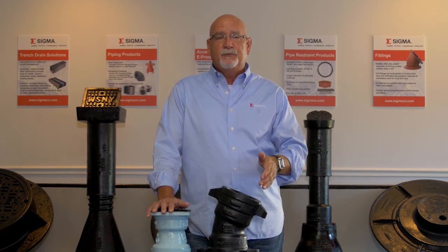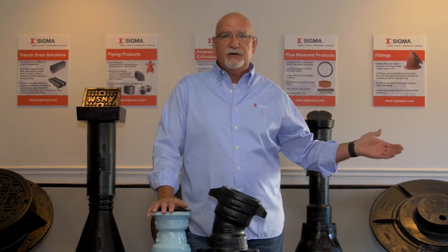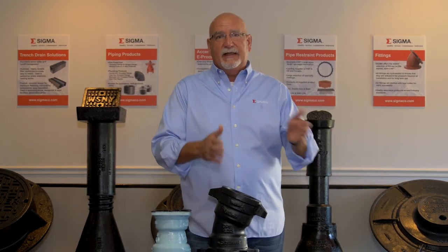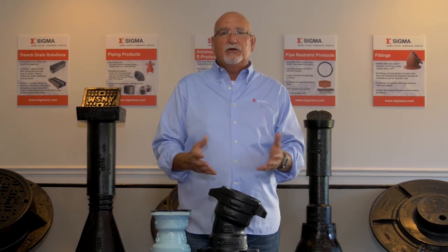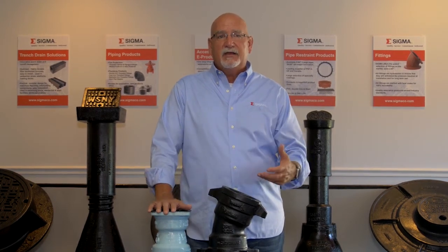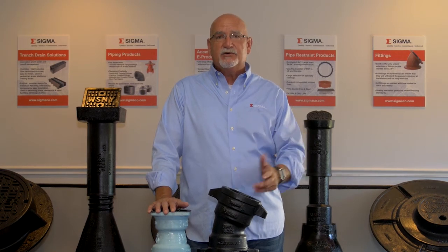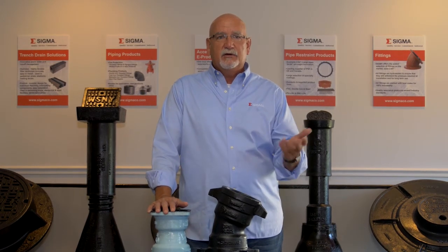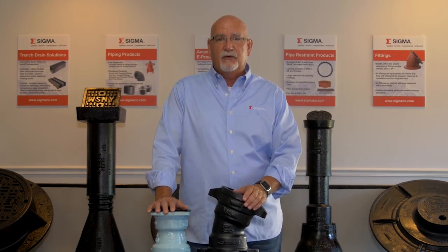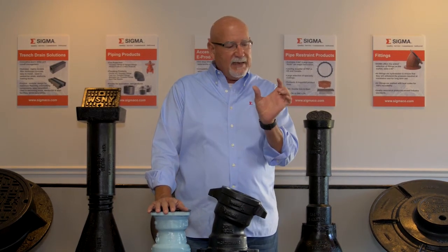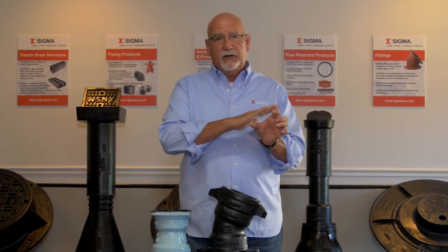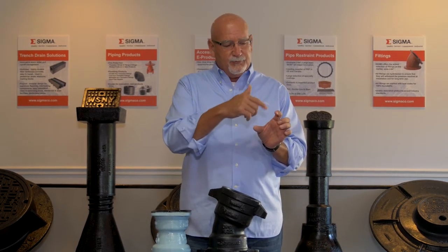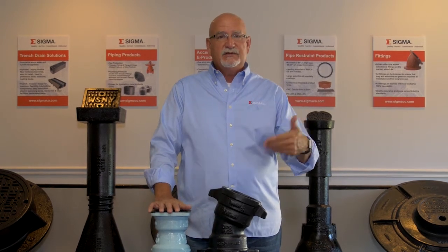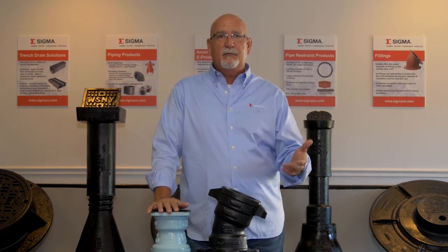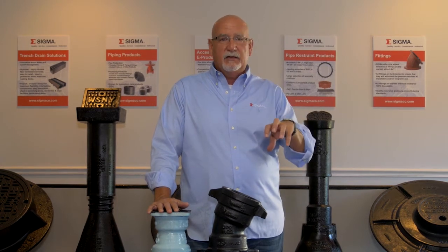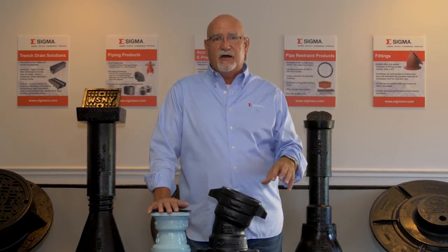It tries to replicate a long period of time in a particular environment in a very short period of time by using aggressive combinations of both time and temperature and concentration of the material that is attacking or being aggressive on the surface. You take a small plate and you make your coating on top of the small plate, you cross hatch it, and over a series of hours you take the plate out and examine how the coating is being affected by the environment that it's in.